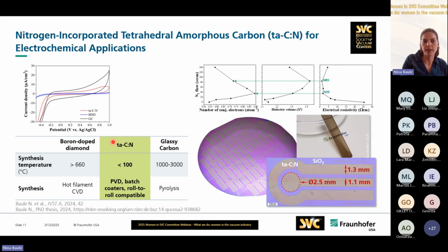amorphous carbon has very much diamond-like electrochemical properties, not just mechanical properties. That means that we have a relatively low background current over a wide working potential window, which you can see over here. And that means for electrochemical applications that you can analyze a variety of analytes at very low detection limits. So compared to, for example, boron-doped diamond, though, which is synthesized at really high temperatures, the amorphous carbon can be synthesized at basically room temperature, and it is roll-to-roll compatible. So the overall scale-up and then economical advantages are very clear. And we can potentially deposit it directly on polymer substrates.